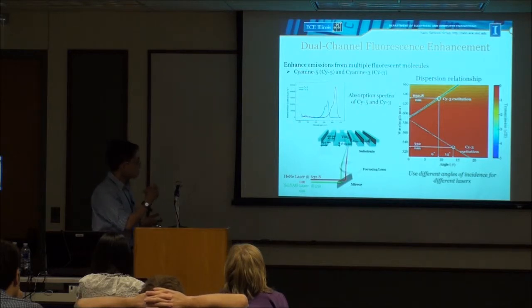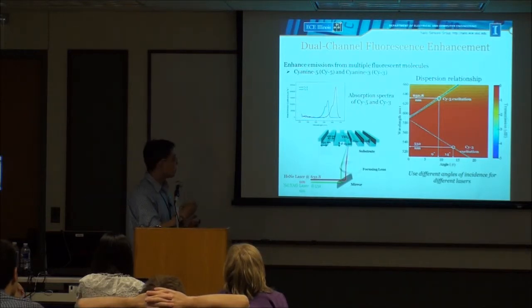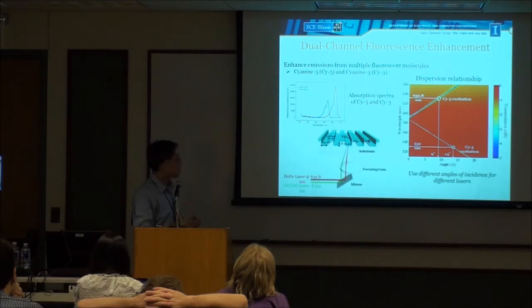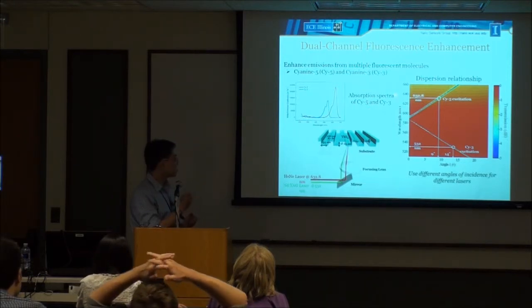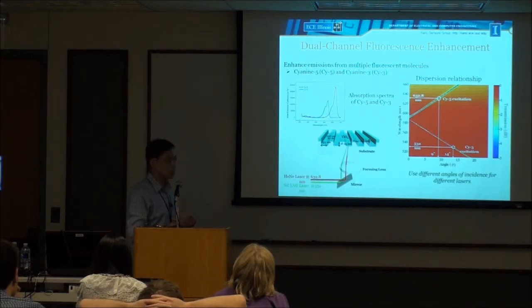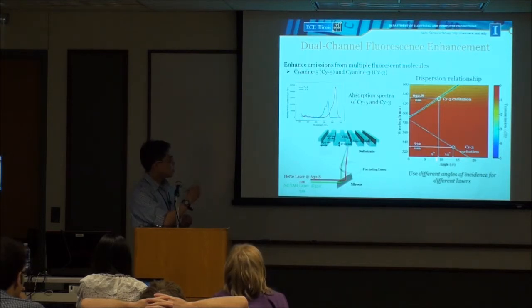So here we demonstrate enhancement of photonic crystal for both Cy5 and Cy3 dye. The absorption spectrum of Cy5 and Cy3 is shown in this figure. So Cy5 has strong absorption at 633 nanometer, and for Cy3, usually people use a green laser as an excitation source. So its dispersion relationship tells us how to get enhancement for both dyes. If you want to excite Cy5 dye, where the excitation laser is 633 nanometer, we have to illuminate the substrate at 9 degrees to couple light into resonance.